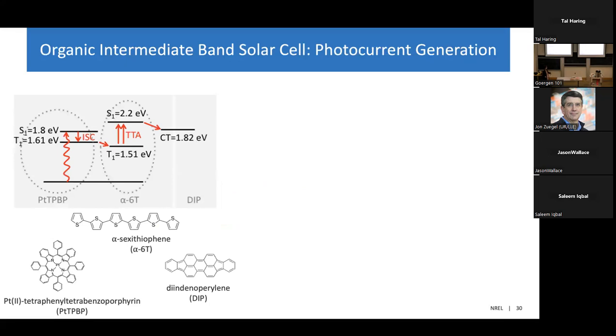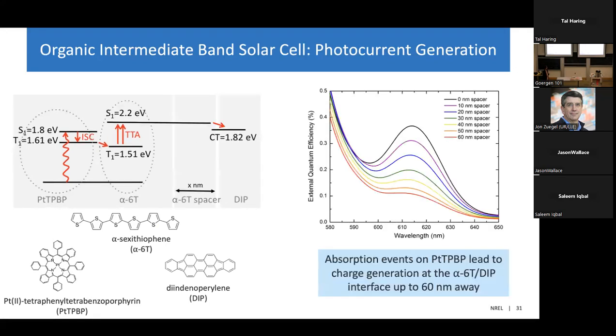And the next step would be to build the actual solar cell by introducing an electron acceptor. So we identified diindenoperylene, or DIP, as an appropriate acceptor for this type of device. And to prove that photocurrent generation due to absorption events on the platinum porphyrin compound were actually leading to free charge in the system, we introduced a neat alpha-6T spacer of varying thickness to separate the site of sensitization from the site of charge dissociation. And here I'm showing a zoom in of the photocurrent output from the solar cell in the wavelength region where the platinum porphyrin compound is absorbing. And even when this spacer thickness is as big as 60 nanometers, we're still seeing a little bit of photocurrent contribution from the PtTPBP. So we can be satisfied that the entire device is operative as we expect.